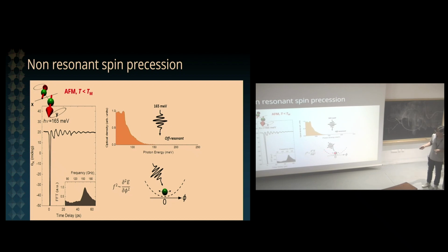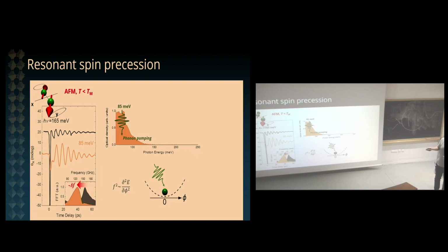So that's a direct probe of the curvature of this magnetic potential. What happens if we now tune the light to be resonant with the phonon mode? Well, one thing that happens is that the amplitude of the oscillation gets bigger. But more importantly, you see that the frequency of this mode has significantly changed. Now there is a red shifting of this frequency down to 120 gigahertz or so.